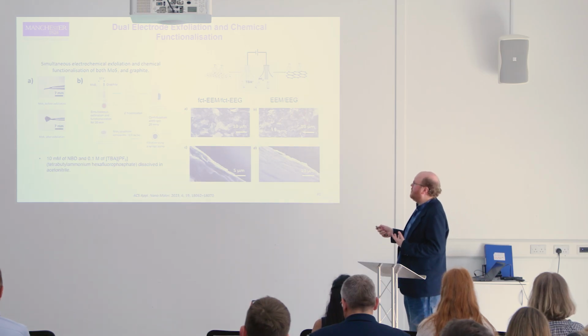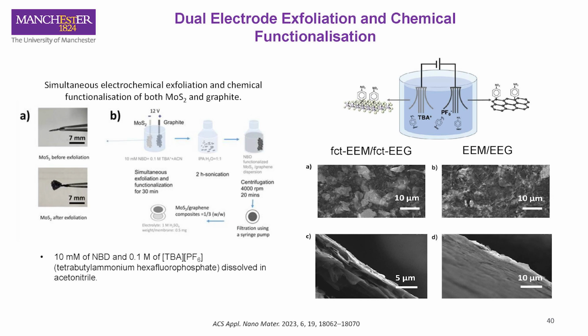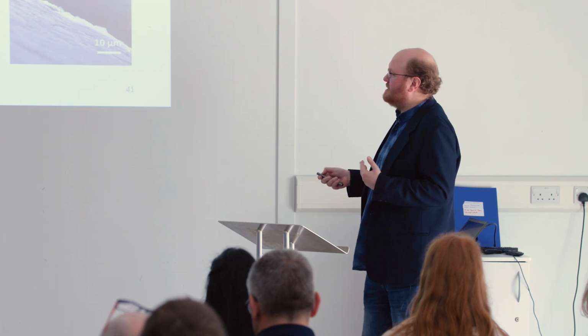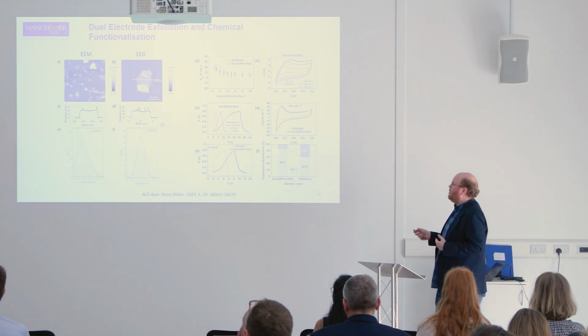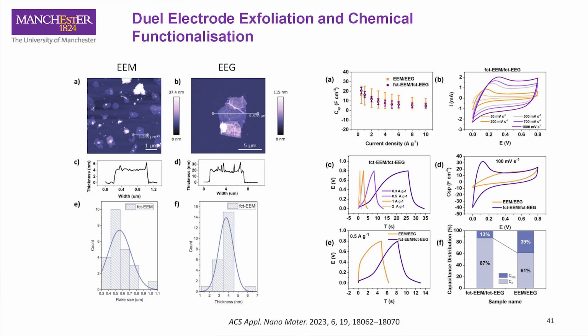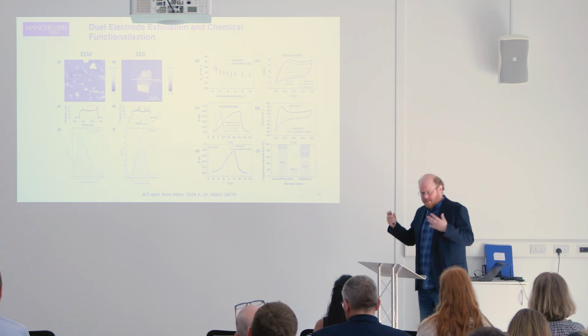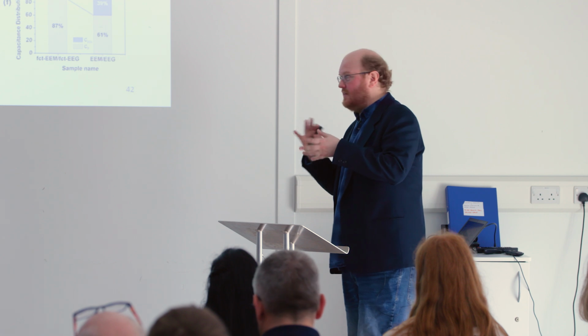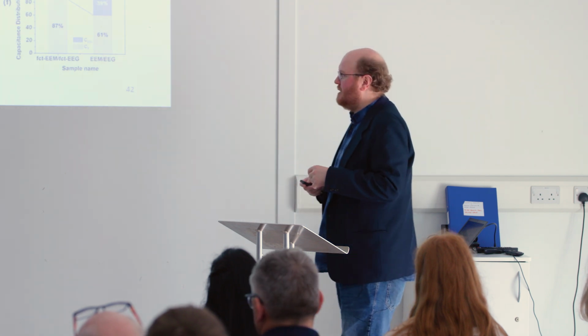So this is just quickly to say, you can also do this where you're electrochemically exfoliating your MoS2 as well as your graphene. In the same way, you've got more parameters and variables to form these layered stacked structures with alternating MoS2 and graphene that can be functionalized. Again, the performance of these is usually much better than the individual materials. You can get quite large flakes here. This is the MoS2, which is very thin, only a few nanometers. The graphene here is a bit thicker, but much larger in lateral size, as you can see. And that's how you can get this interaction between the different layers.